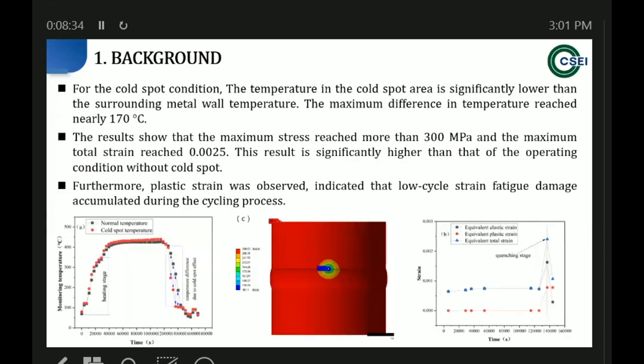And for the cold spot condition, we consider a cold spot. We can see the cold spot has a lower temperature compared with the surrounding metal. And here we can see the maximum stress reached more than 300 megapascal. And this may cause plastic strain and also low-cycle strain fatigue damage for this material.